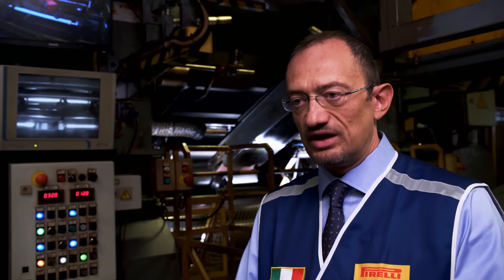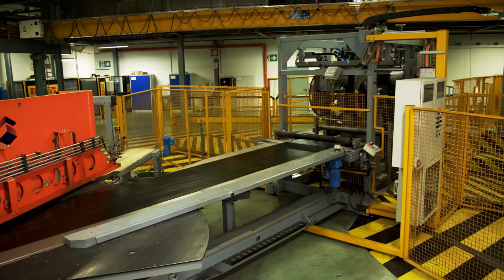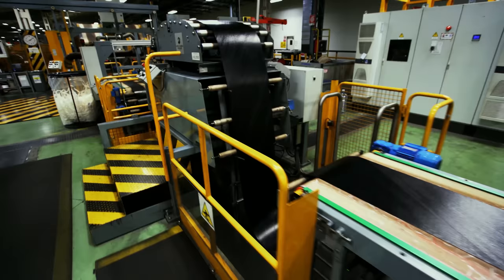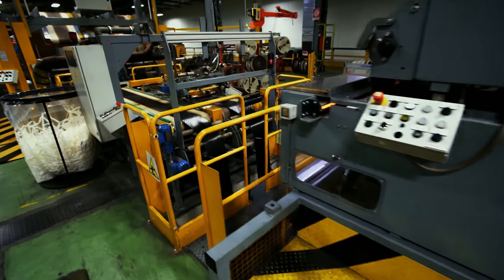Once the metal cord has been encased in rubber, it is cut by the machine. This sheet will later form the steel belt needed to manufacture the P Zeros. The cut must be angled so that the fibers in the finished tire run perpendicular to the direction of travel — this is necessary for the steel belt to withstand high speeds. A similar process is used to create the fabric-rubber composites used on the insides of the tire — the carcass — which also gives the tire its stability.